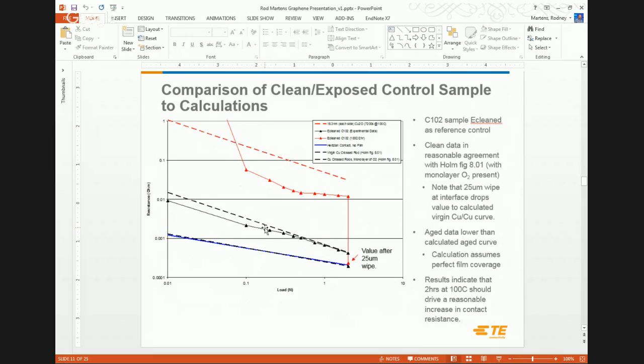I took a copper coupon and then we electrocleaned it. So basically we etched all the oxide off and got down to bare copper, but then it's exposed in the laboratory environment. You can see we got very good agreement experimentally with the dashed line there. So, okay, good. We have a good foundation to work from.